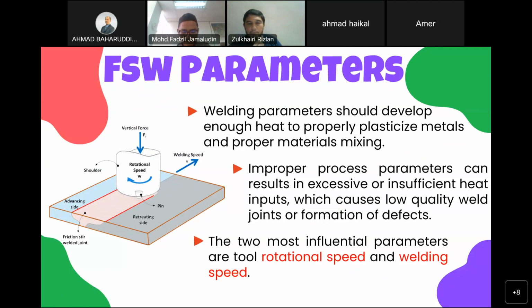So these two parameters are the most responsible for heat input variation in friction stir welding. For example, if the rotation speed is high, then the heat input will be high as well. And contrary to rotation speed, for welding speed, if the welding speed is high, the heat input will be lower.